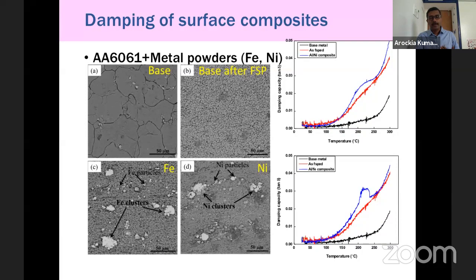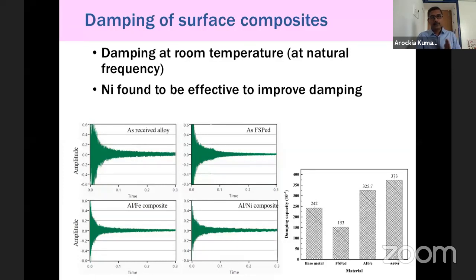And not only ceramic particles, if you incorporate iron or nickel into the 6061 alloy, that also increases the damping, and that's what I'm showing here. In all these cases, by incorporating nickel or iron, we were able to improve the damping. In this plot also, this is for the as-received material, and this one is for FSP. But if you see the bottom 2 plots, when you incorporate iron or nickel, the damping is greatly improved, and that's what we are seeing through these plots.